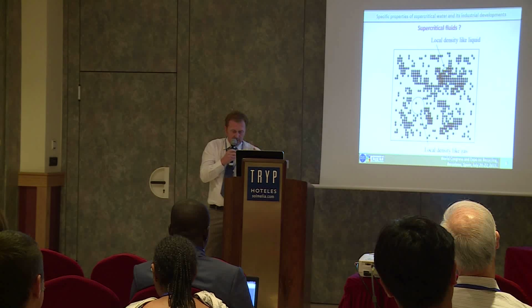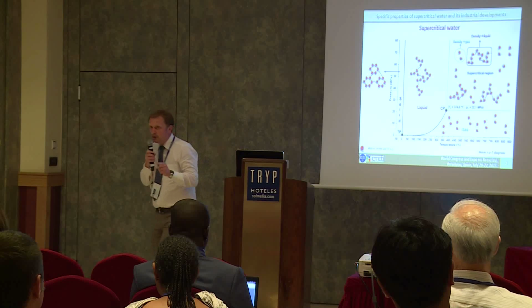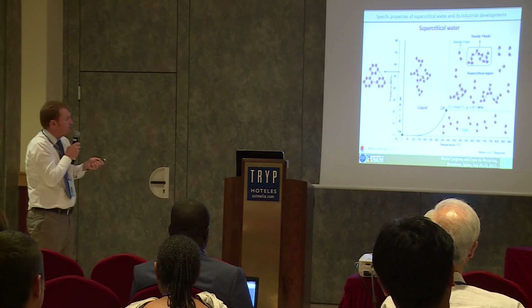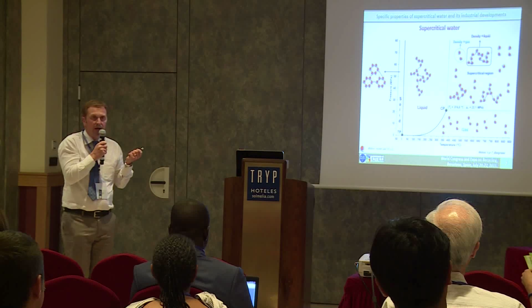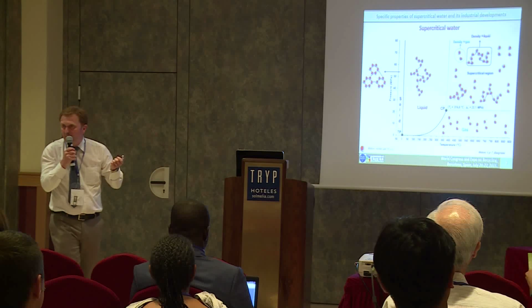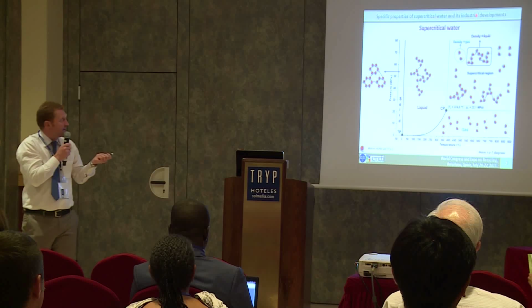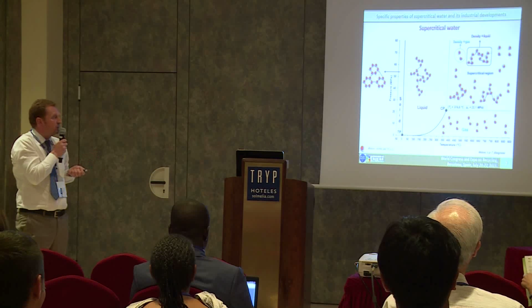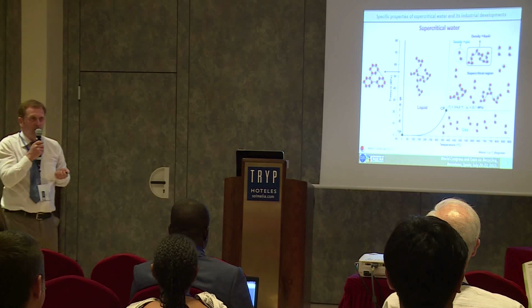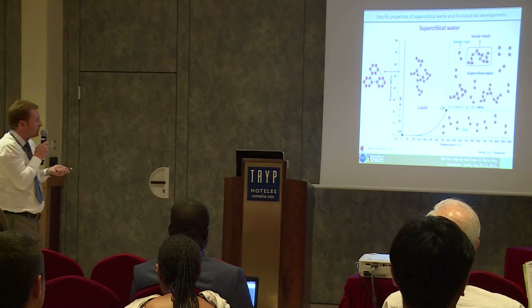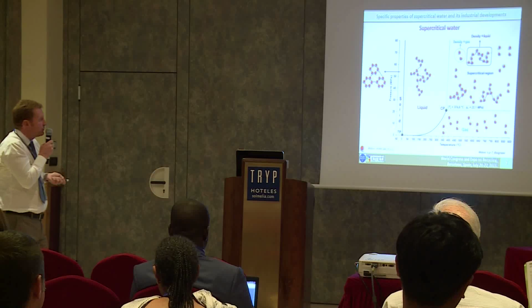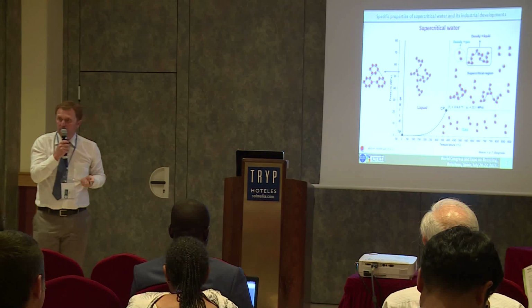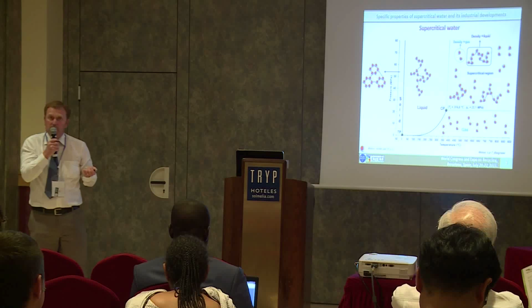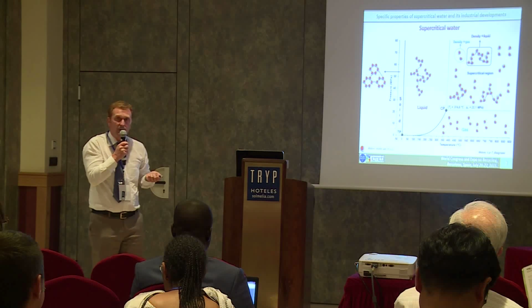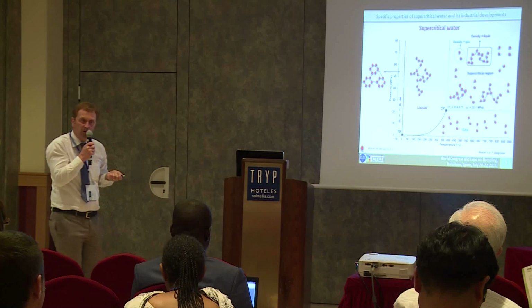This is valid for all fluids under supercritical conditions. Water is a very good solvent and exhibits specific properties due to the hydrogen bonding, which is not present in other kinds of solvents like CO2, for instance. And this solvent we have used to develop our technology for the recycling of carbon fiber from CFRP. Now you see, it's much more difficult from a technical point of view in comparison with CO2. The critical temperature of water is 374 degrees Celsius, and the critical pressure